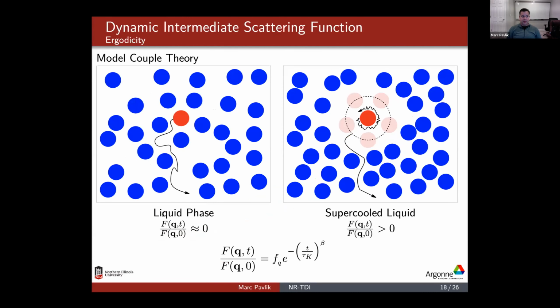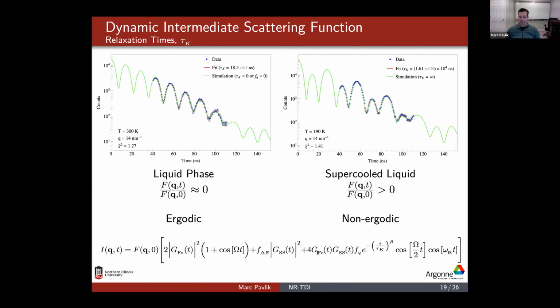Going back to the previous few slides, we want to talk about the intermediate scattering function and what destroys that third term. Using mode coupling theory, when that intermediate scattering function is approximately 0, we consider that sample in the liquid phase. Whereas as we start to cool the sample or go to the supercooled regime, that intermediate scattering function is no longer 0, and we can start measuring what the relaxation time is throughout this process. So here are 2 examples. The blue is actual data, the red is the fit, and the green is the simulation.